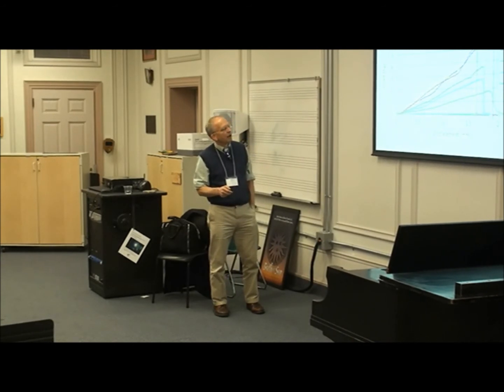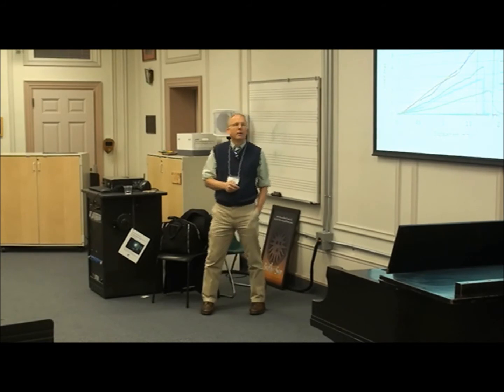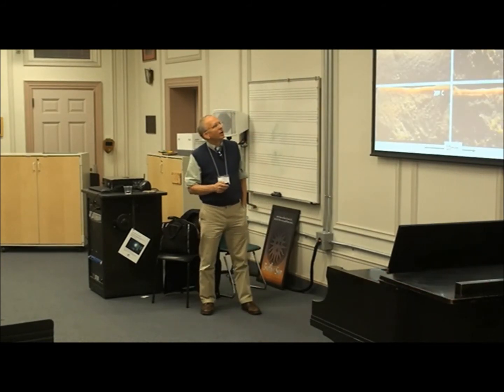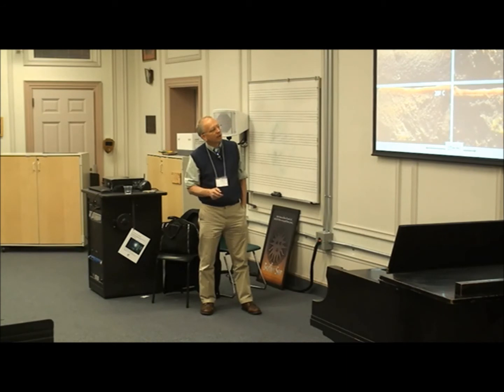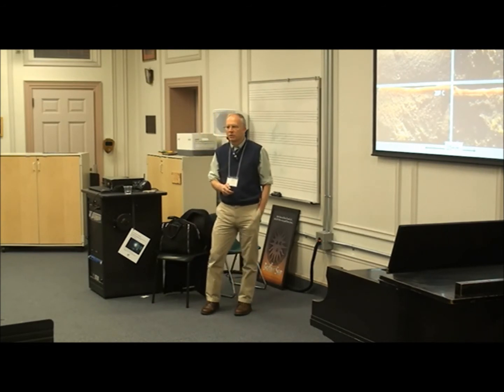So this is 35. It's getting pretty soft there. It's almost at its melting temperature. 10, it's kind of stiff there, so it's kind of cold for this material. Does anybody know what the material is? So here it is, here's the fractography, and you can see it changes markedly from 10 to 35 degrees. So as it gets warmer, the fracture surface changes clearly, right? So we measure the fracture surface.